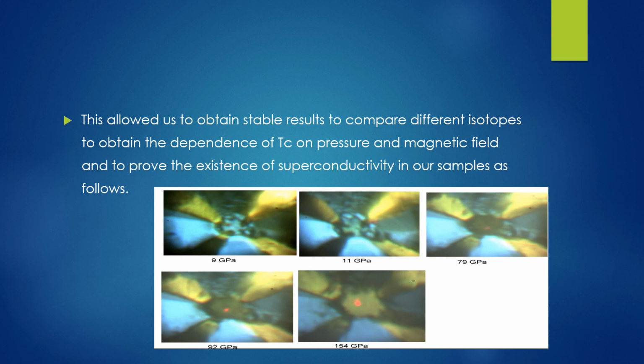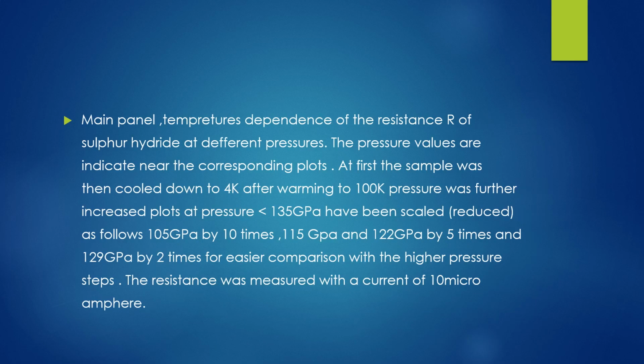This allowed us to obtain stable results, to compare different isotopes, to obtain the dependence of Tc on pressure and magnetic field, and to prove the existence of superconductivity in our sample. These pictures show that at different pressures, superconductors show different properties. In the main panel, temperature dependence of the resistance of sulfur hydride at different pressures is shown. The pressure values are indicated near the corresponding plots.